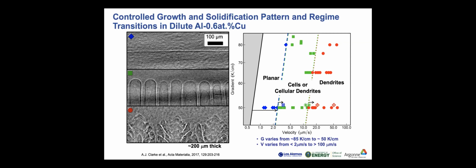So the question becomes why? We think this is due to convection effects, which hopefully I'll convince you of in the next slide. With these dilute aluminum-copper types of compositions, it's very hard to see contrast in the melt. So I'm going to show you an example for a tin-bismuth alloy where we see things a little more clearly. This is a higher density alloy.